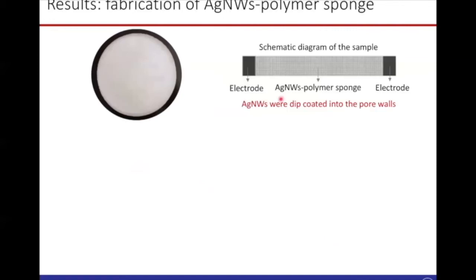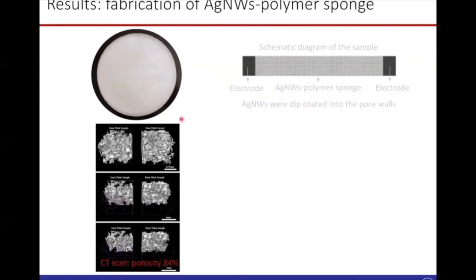Now, to prove this concept, we first fabricate a polymer sponge, and then we cut it into a small strip, and then we add 2 electrodes, one on the left and one on the right side. And in the middle portion, we coated silver nanowire through a method of dip coating. We analyzed this sponge first in a CT scanner to make sure that the pores are well connected and the size of the pore is quite matched with that of the silver nanowire. So when you dip coat, the silver nanowire will deposit on the pore walls and you get a conducting nanosponge.